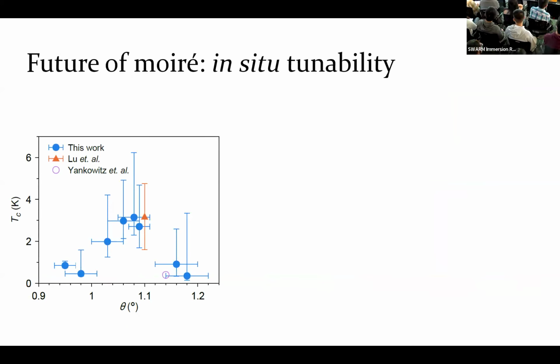But now, I put a lot of hype here, but I want to also say that there are some caveats of this twisting that I haven't mentioned to you yet. I tried to frame it as if twisting is as good as gating, but it's not, at least yet. The main reason is that when we make these twisted samples, either of graphene or any other 2D materials, once you put down the 2D materials together and they're stuck, you cannot change their twist angle anymore. So it's kind of a one-shot process.